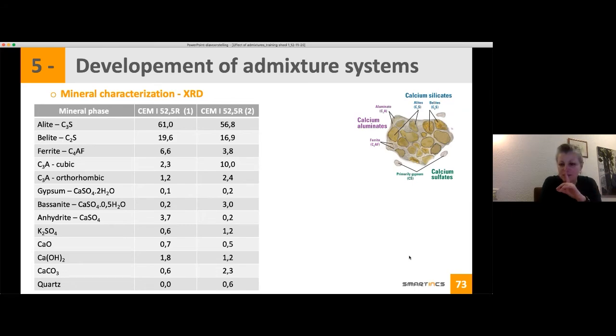And I will mention that the admixture was a PCE. So if you look at the interaction between your PCE and your cement, what will be the primary interaction? It will adsorb, but on which phase? It has the interaction with the alite. Not the first. The first interaction is with your C3A, so with your aluminate.